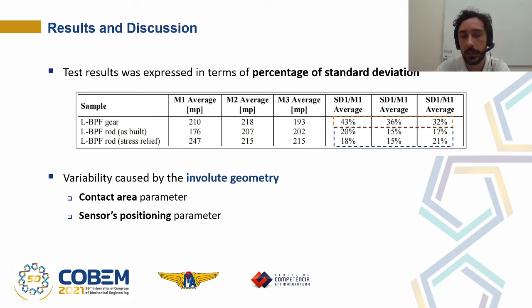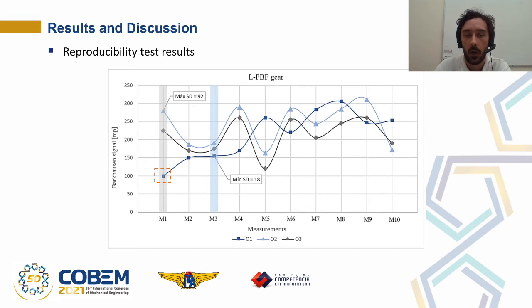This fact demonstrates that factors such as the sensor's contact area with the sample surface and the positioning of the sensor itself can cause significant signal deviations in the results. Observing the results for each operator, it can be seen that the greatest variation of the signal in the sample with involute geometry is a trend, showing the difficulty of measuring due to geometry.